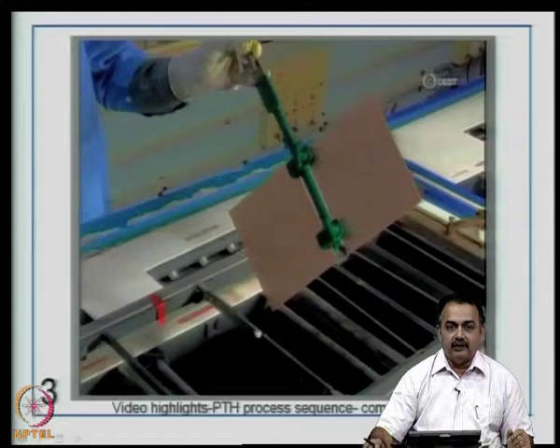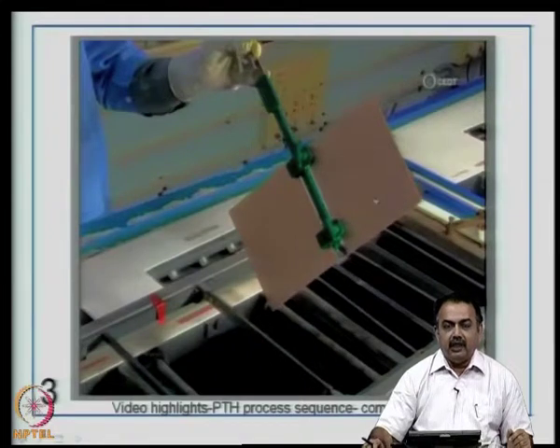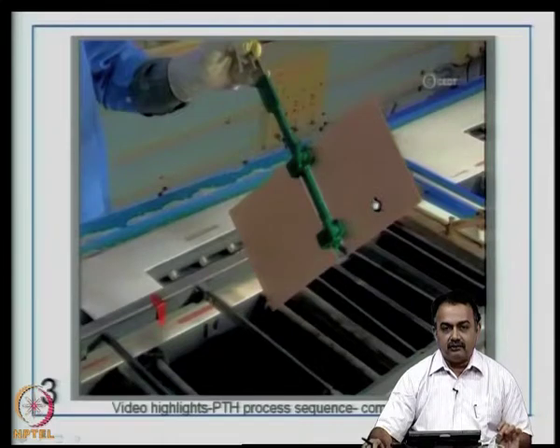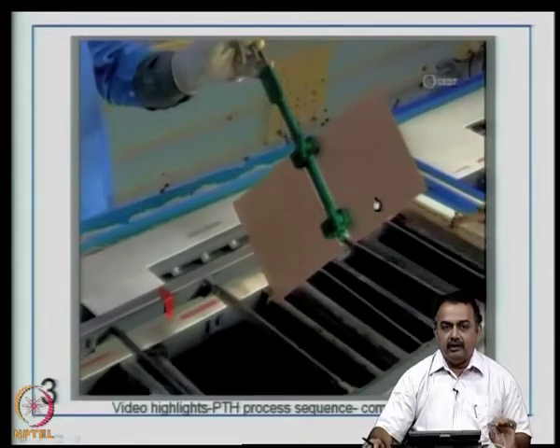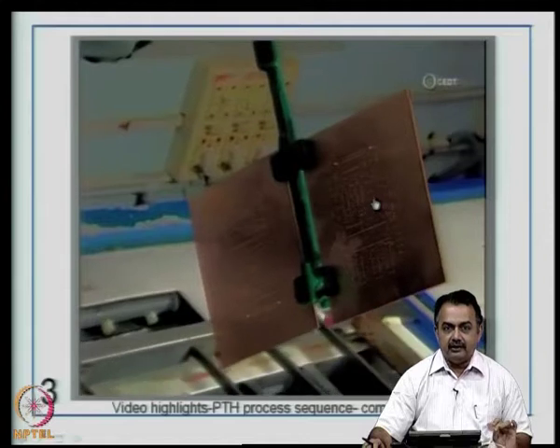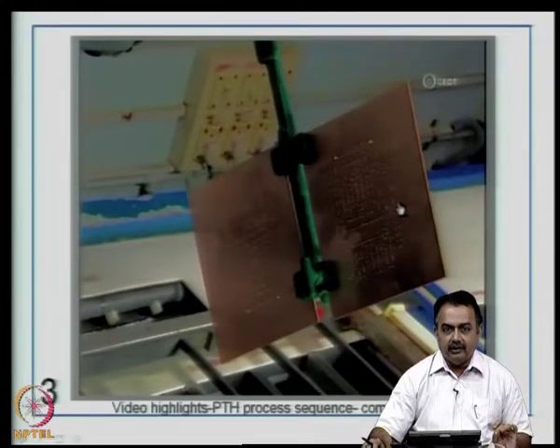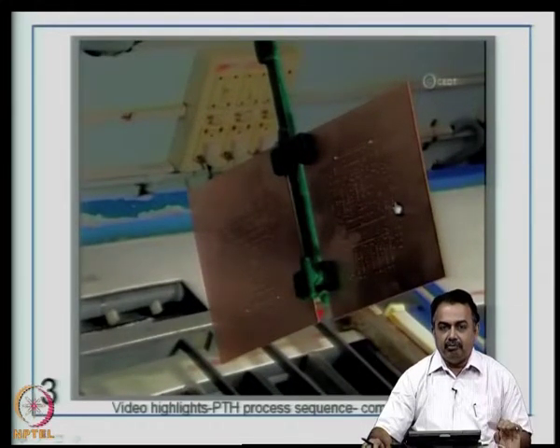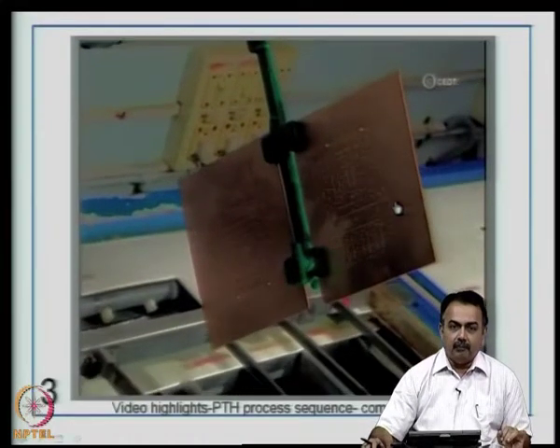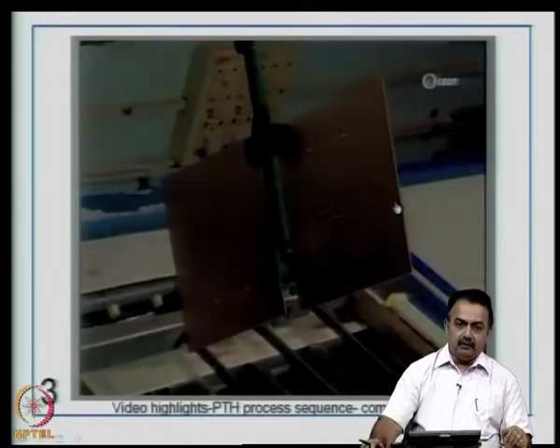You can see that this panel is very shiny, a good coverage of copper has taken place on the entire surface of the panel, and if you go deeply and carefully into the microscope at this stage to look into the through holes, they will be well plated. You can see from a side shot here that the holes are well plated with the pure copper. Now, again this is going to be a key step. As the name indicates, in panel plating the entire board is plated.